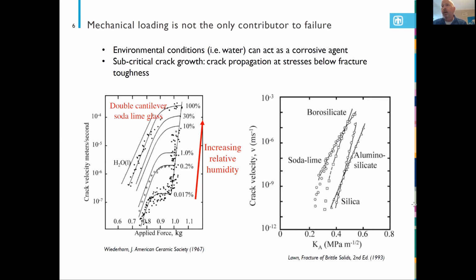Now, today I'm going to be talking a lot about fracture toughness, and fracture toughness has a very specific meaning. It is the stress state of a given material that is necessary to propagate a crack. And so these subcritical crack growths are associated with stress states that are below the fracture toughness. So about 50 years ago, one of the seminal works describing this type of behavior actually showed that as a function of relative humidity, increasing relative humidity, the crack velocity increases. But I must note that all of these data points here are at stress states that are subcritical. And so this really highlights the fact that it's not necessarily mechanical loading that forces cracks to take place. What's referred to as subcritical or slow crack growth can occur as a chemistry or as a chemical interaction.